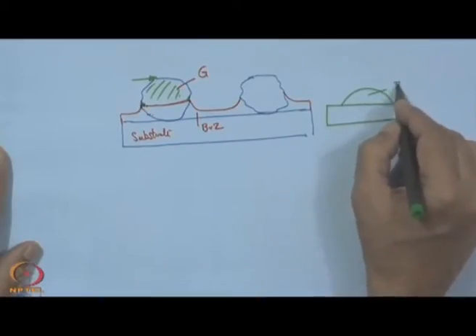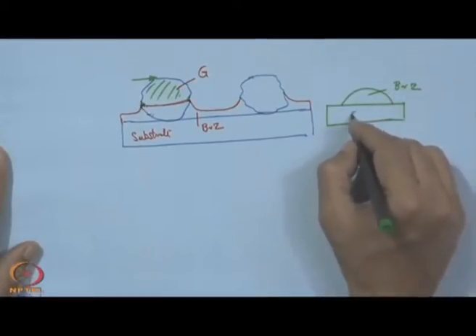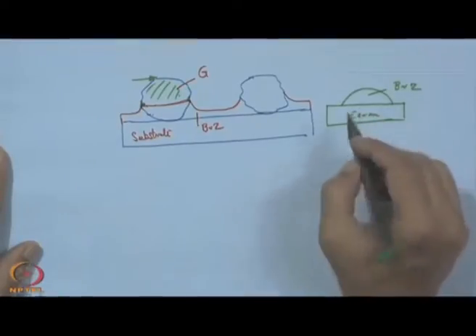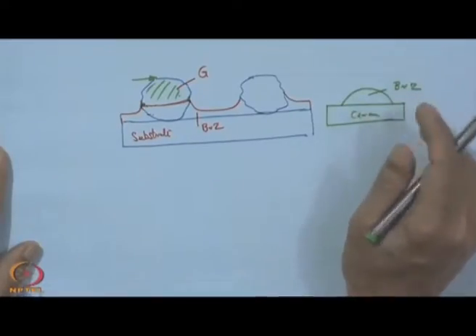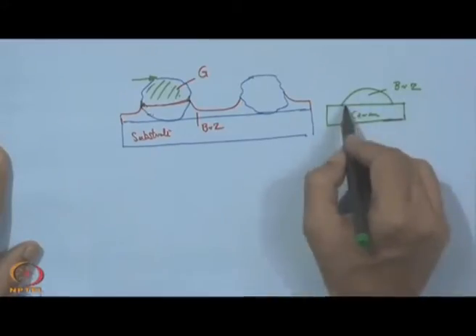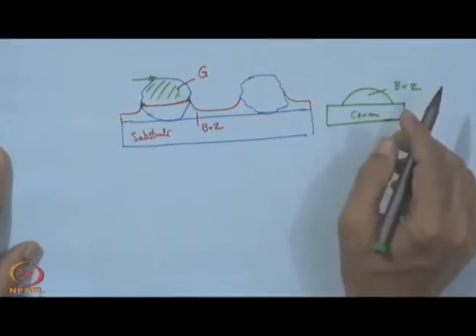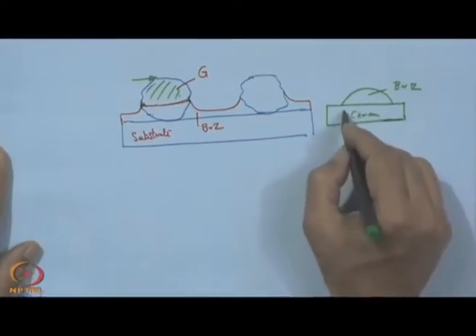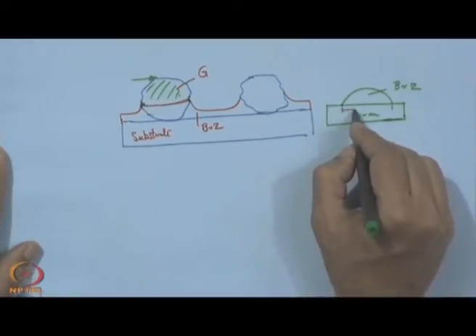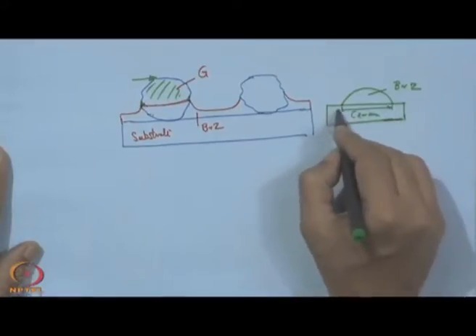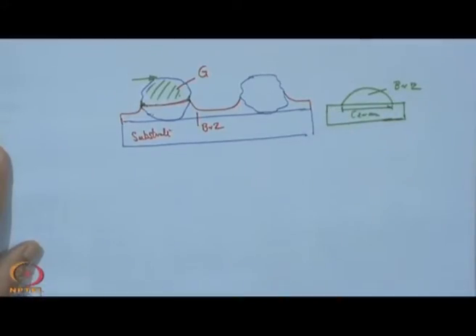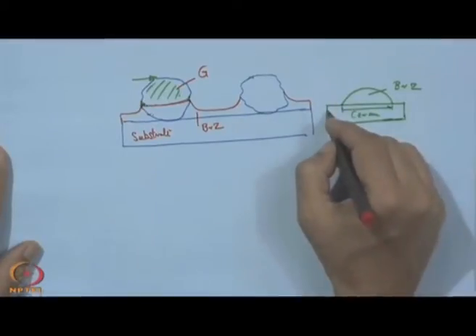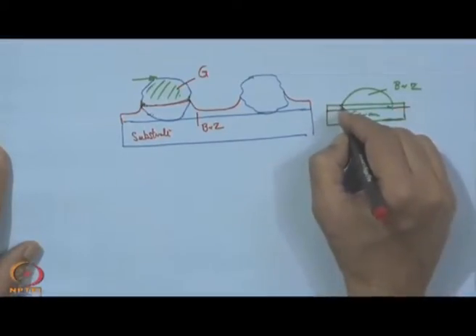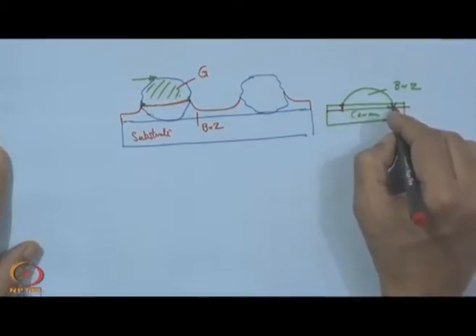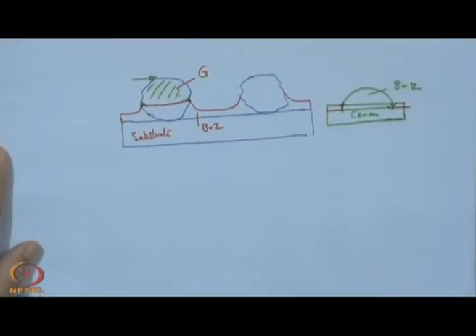So, if this is the braze alloy and this is the ceramic, then we see that when it is under the solidification process, that means after melting it is being solidified, in that case also the portion of the ceramic within this zone will be under compression. However, this part will be under tension, it is free, this part and this part, and as a result we may also find a crack. So, this crack and this crack are very similar in nature.